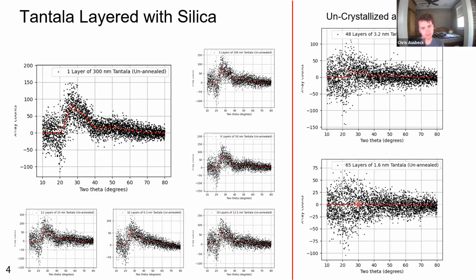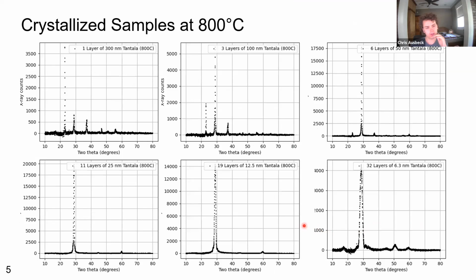We believe what's causing this is that once you get to 3.2 nanometers and 1.6 nanometers, those distances are very close to the actual size of a tantalum molecule. So we believe the silica is very close to interacting with the tantalum molecules and therefore causing the tantalum amorphous peaks to broaden out so much that you can't see them at all. Of those samples, 6 of them, which are the 6 thickest ones, have crystallized at 800C, and the 2 that you saw that had the diminished amorphous peaks have not crystallized yet.